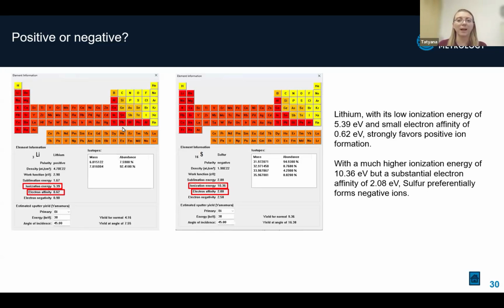This makes it an excellent candidate for detection in positive mode. In contrast, sulfur represents why some elements can be measured only in negative mode. It has a much higher ionization energy of 10.36 electron volt and substantial electron affinity of 2.08 electron volt. Sulfur preferably forms negative ions during the sputtering process.